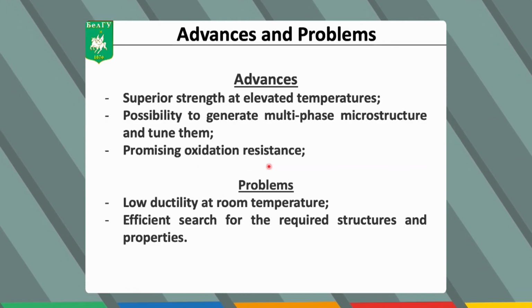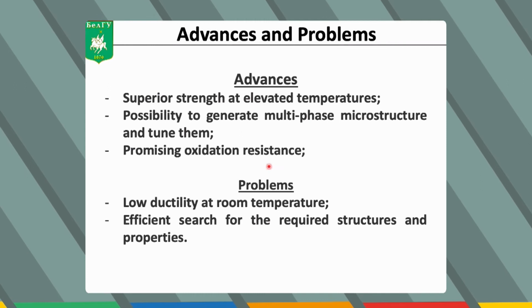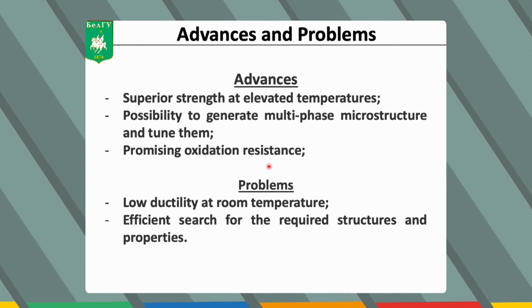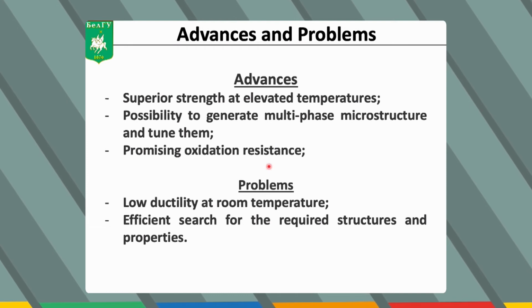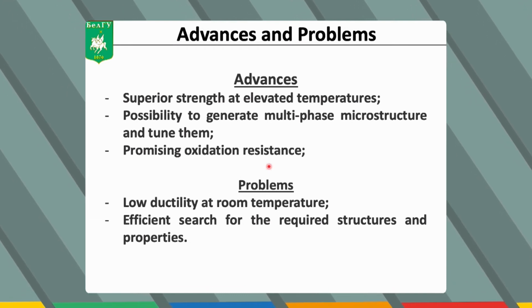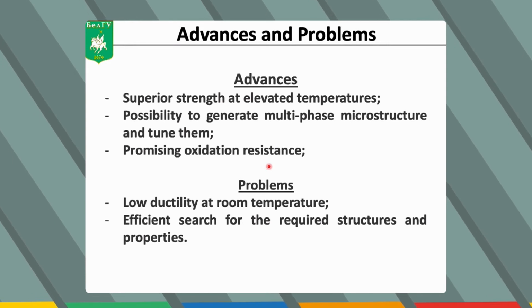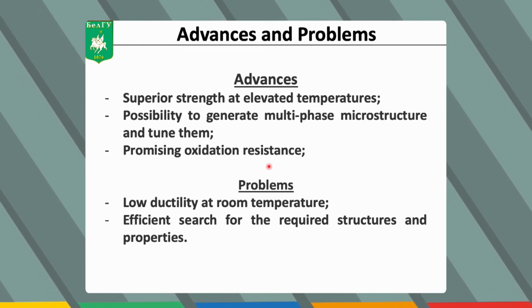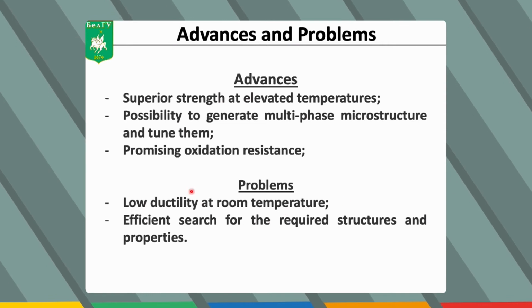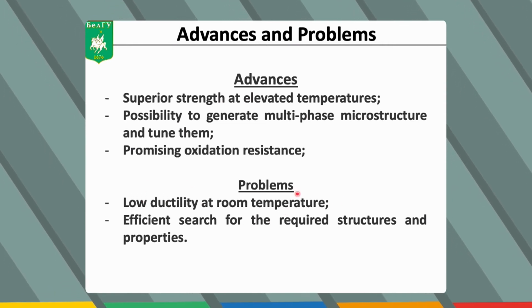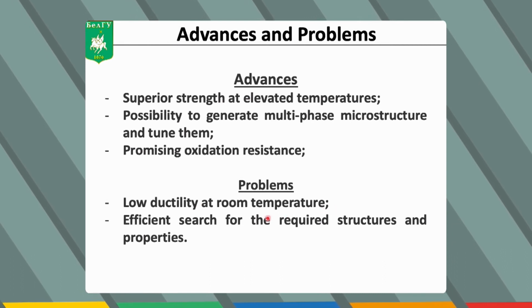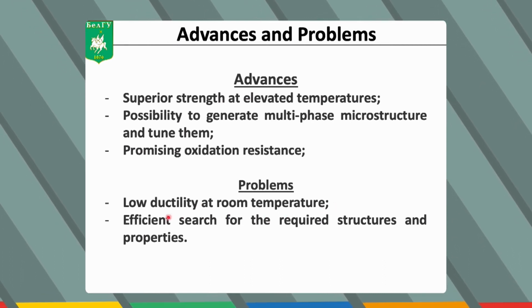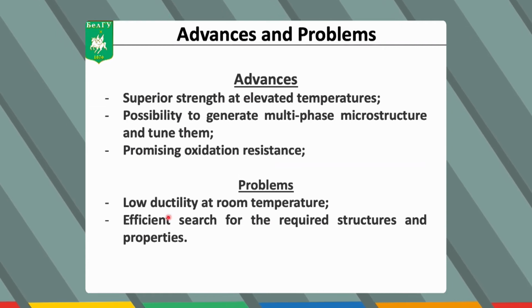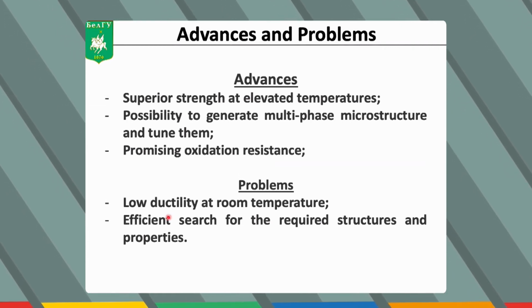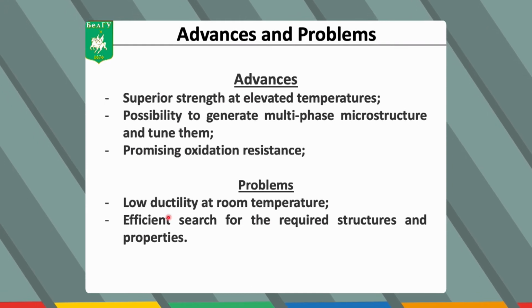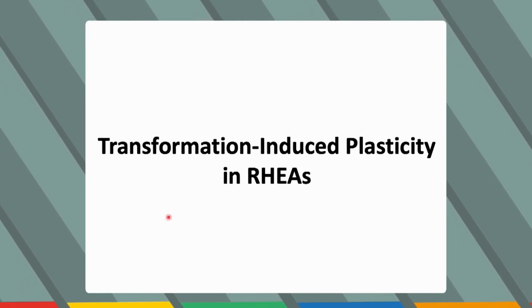And a short summary on this section is that the refractory high entropy alloys offer very attractive strength at high temperature and also promising oxidation resistance. However, there are some problems. One of them is associated with the general low ductility at room temperature in most alloys. And the other problem is that we need some tools to effectively search for the most promising compositions and structures and properties. And now I'll show how we're addressing these issues in our lab.